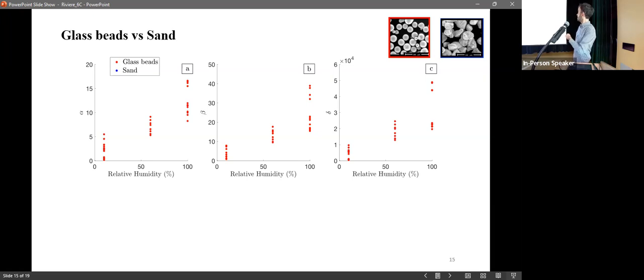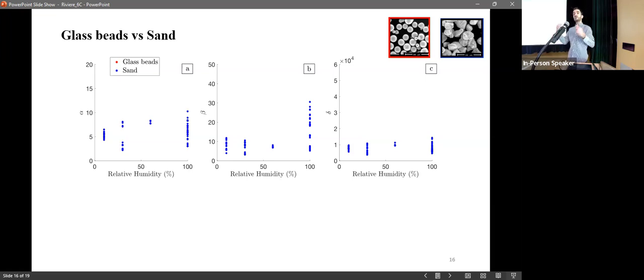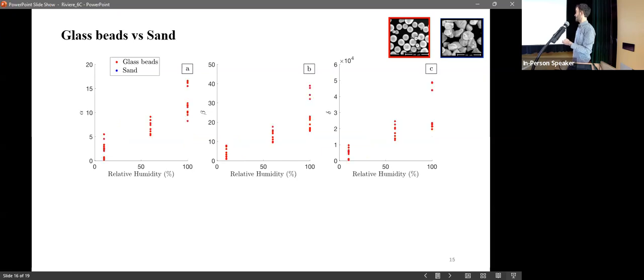So she has been doing measurements in sand samples as well. In that case, we see that when we change relative humidity, we don't see much change in nonlinear parameters. What we think is happening is that because the grains are very angular in sand, when we humidify the sample, the grains are locked, the assembly is locked, and the water is not able to weaken the junction. So this is a comparison between the two. This is kind of flat, there's some scatter, and this is increasing, and this is the two together.